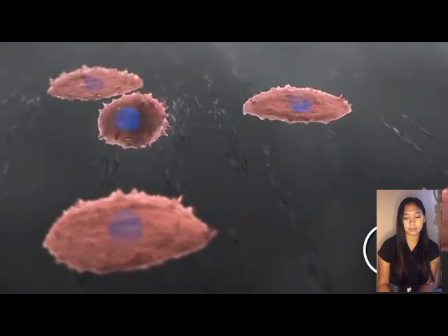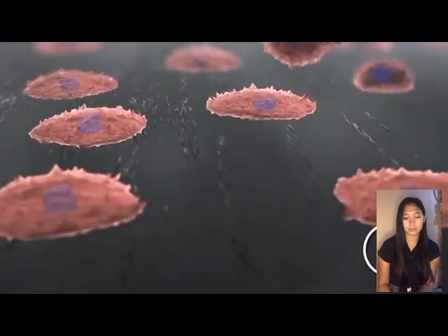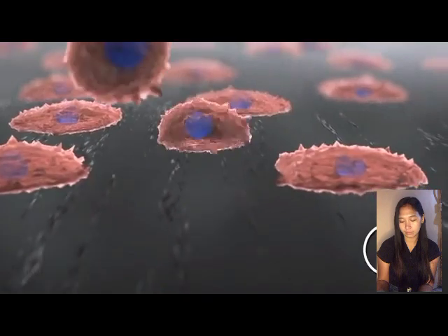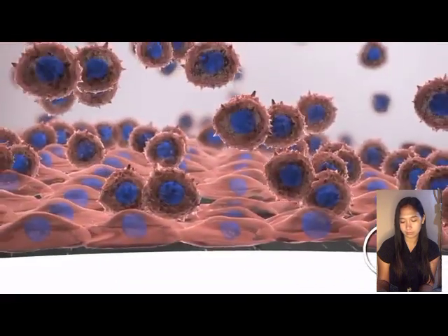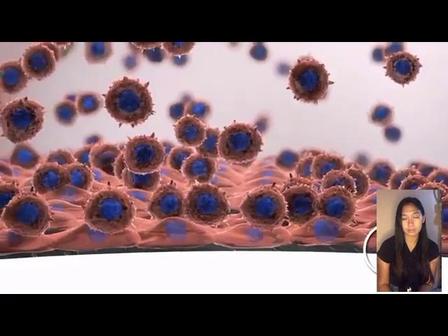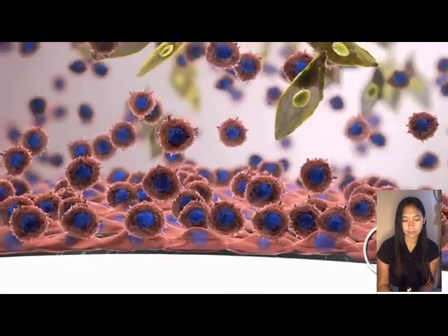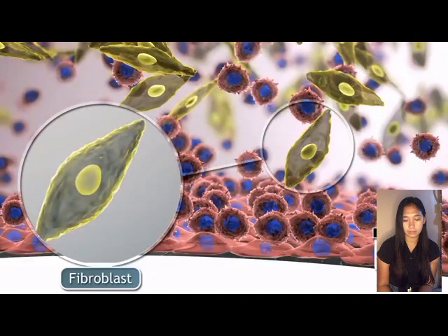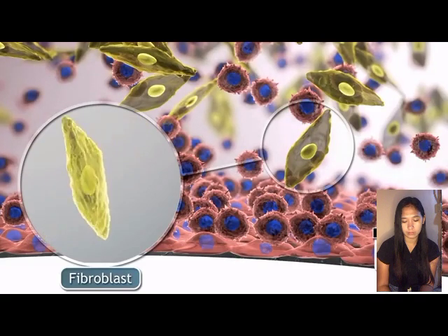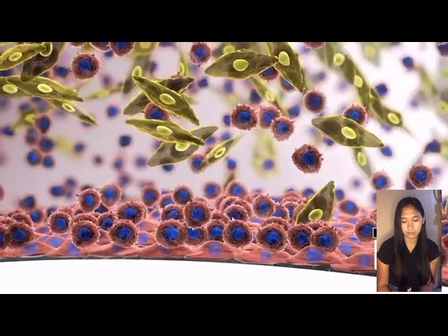Ever more macrophages are attracted chemotactically to the site, where they form the early foreign body granuloma. It takes only a few hours for the mesh to be enveloped and fully covered by the macrophages. During release of the messengers, other important cells are also attracted, in particular fibroblasts, which are responsible for the cicatricial envelopment of the mesh. Even on day 1, many fibroblasts are present which form an early perifilamentary scar.